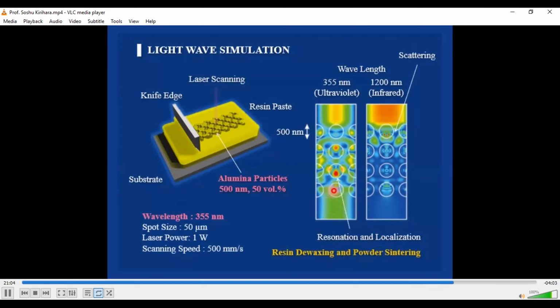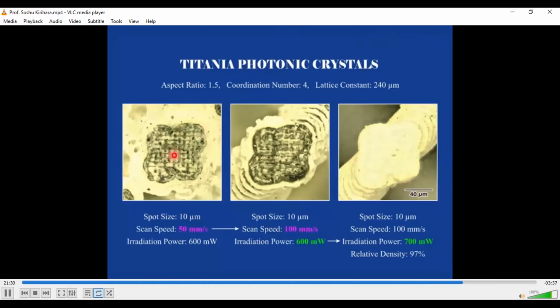Anyway, by a layer by layer stacking process, we can create micrometer order 3D structures. In this case, titania photonic crystals were created by an ultraviolet laser scanning process. At first, here is a micrometer order structure. However, in this case, the nanoparticles were coagulated in the 3D structures. So the scanning speed was increased two times, to 100 millimeters per second, so we can obtain more clear micrometer order structures.